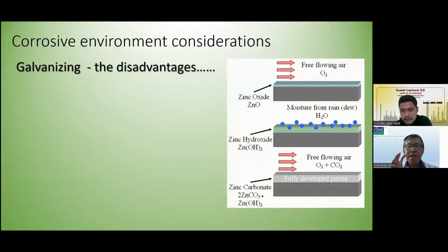Now, in the atmospheric environment, when a galvanized steel has the zinc layer exposed to the environment, in the common environment where oxygen is easily available, and due to flowing air, it gets moisture due to rain, due to dew, condensate on the surface of the zinc layer, because internally it should be steel. That's what we call galvanized steel. So zinc is only at this outer layer facing the external. So when the water, the wetness comes in together with the oxygen, then it will start to form zinc hydroxide here. So zinc hydroxide is not a good product. Sometimes we call it a kind of white rust.